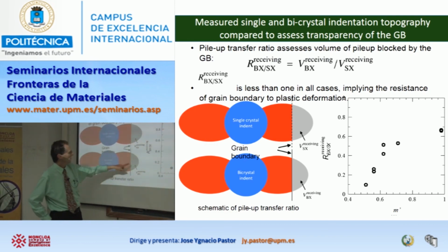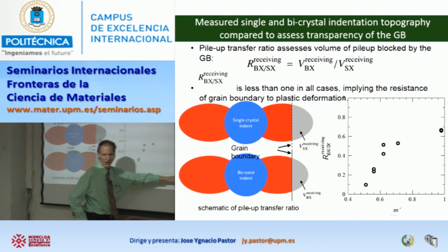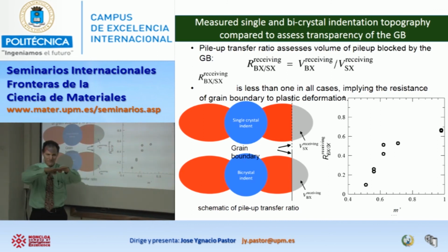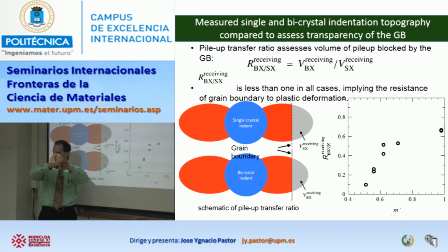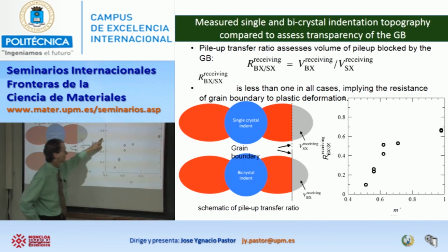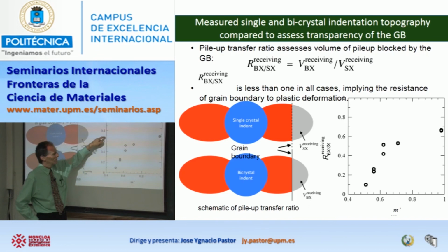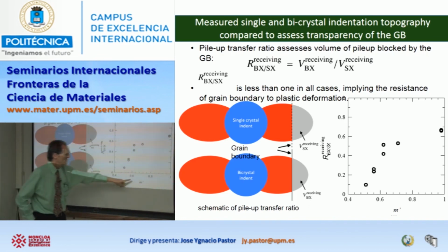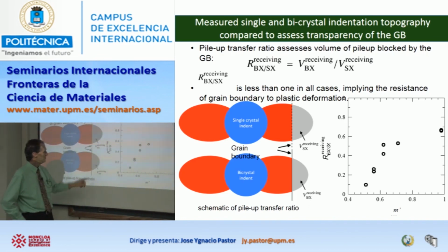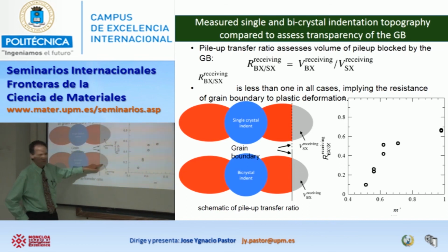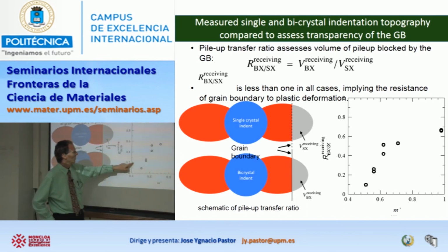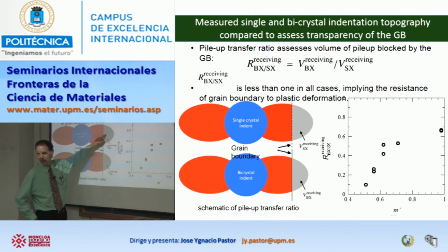And when I have an M prime value that is 1 or near 1, meaning that the grains are very slightly misoriented from each other, I get a value of 0.6 or 0.7, somewhere in there. But if I go to M prime values that are lower, then this becomes much smaller, say only 20% of the volume that's here. So thus, I have a way of figuring out how potent is the grain boundary for